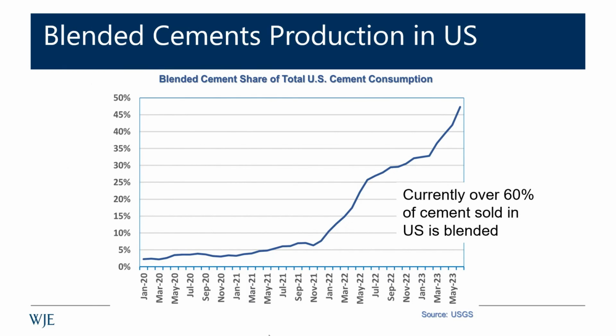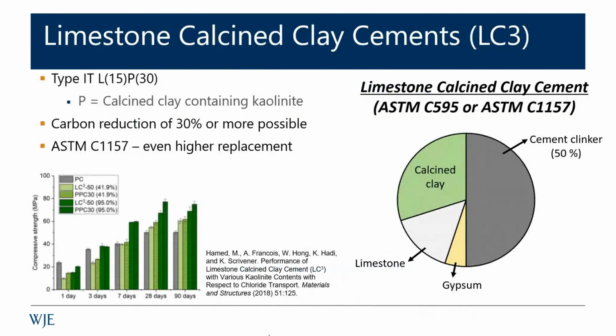Another type of cement that likely will begin to get used is limestone calcined clay cement. I'm not going to go into any details on that right now, but you may hear about it. As you can see just in the description, typically you're looking at maybe 50% clinker, 30% calcined clay, 15% limestone, something of that type, roughly. So it's a way to balance out a further clinker reduction using a calcined clay as an SCM with higher blends of limestone that's very specifically designed to work within that system.